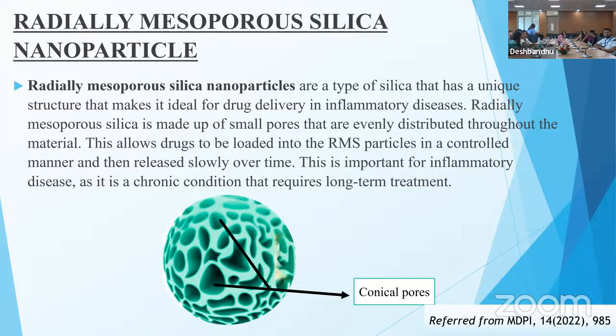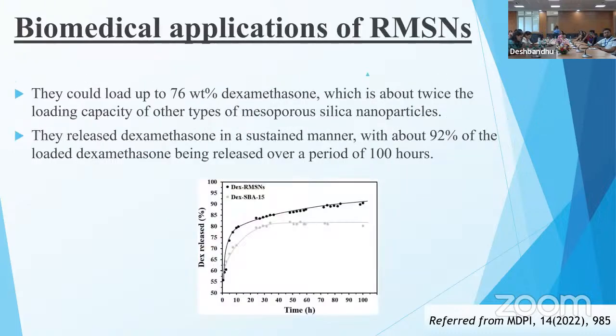There are various biomedical applications of radially mesoporous silica nanoparticles. One of the applications is that they can be coated with dexamethasone, a glucocorticosteroid, and used in the treatment of rheumatoid arthritis. In this research, they concluded that RMSN, when coated with dexamethasone, have a high loading capacity of about 76 weight percent compared with the other nanoparticle, that is SBA-15 mesoporous nanoparticle. The drug loading efficiency was twice that of RMSN compared to the other nanoparticles.